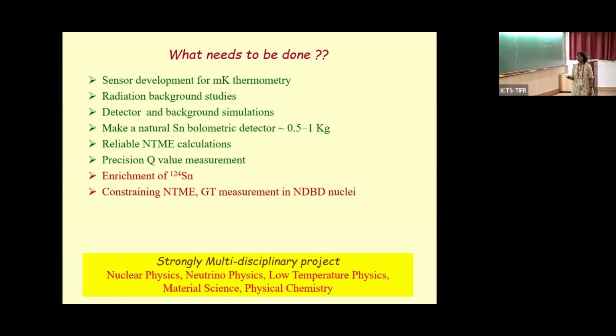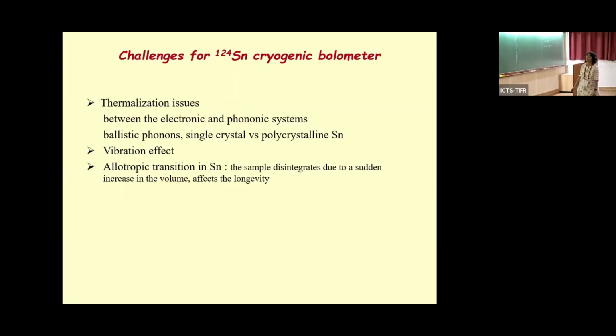So as you can see, if you look at different aspects, this is a very strong multidisciplinary project. There's nuclear physics, there's neutrino physics, which is obvious. But when we go for the millikelvin detector, there's low temperature physics, there's material science and physical chemistry also. And of course, engineering is there because you have to make this large size detector. The specific challenges in coming to the cryogenic bolometer are also the thermalization issues. Usually people do these low temperature bolometers out of insulators, because the low temperature specific heat goes as T cubed, so it is small. But in the case of superconductors, there is a slight issue because there is a decoupling between the electronic and phononic systems, so you don't get the full energy deposited. So there are studies which you can do.